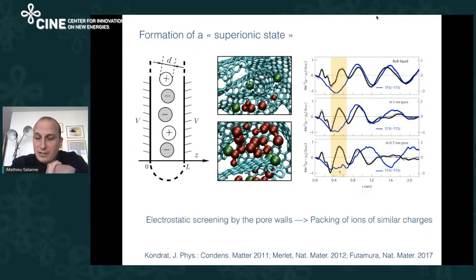And it's only in 2017, so 5 years after the simulation, 6 years after the theory, that by doing in situ X-ray with a group of Kaneko in Japan, they were able to show that these arrangements are indeed present in the systems. And in fact, it's seen by these,